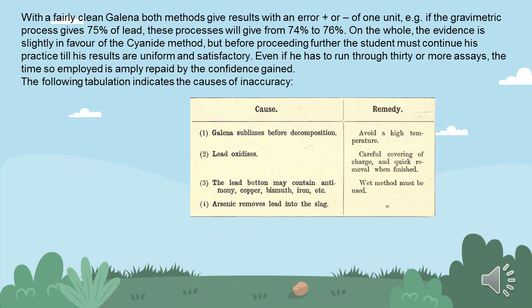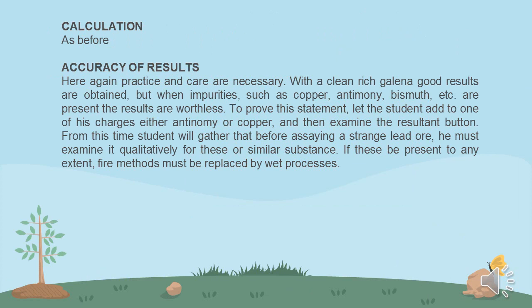With a fairly clean galena, both methods give results with an error of plus or minus 1 unit. For example, if the gravimetric process gives 75% of lead, this process will give from 74% to 76%. On the whole, the evidence is slightly in favor of the cyanide method, but before proceeding further, the student must continue his practice till his results are uniform and satisfactory, even if he has to run through thirty or more assays. The time so employed is amply repaid by the confidence gained. The following tabulation indicates the causes of the inaccurate results. Calculation as before. Accuracy of result: here again practice and care are necessary. With a clean rich galena, good results are obtained.